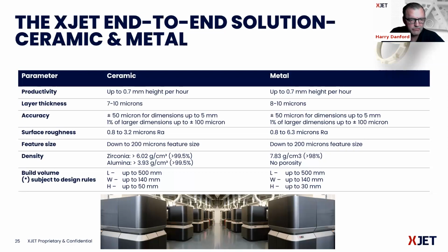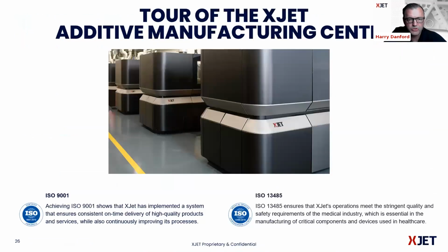In terms of the densities that we're achieving, basically for ceramics, 99.5% full density, kind of the standard density in terms of grams per cubic centimeter for those particular materials. And then 98.5% for the stainless steel products. The size of the tray for the Carmel 1400 system is 500 millimeters in length, 140 millimeters wide. And then in terms of Z height, our current capability for the ceramic materials is around 50 millimeters, so a little over 2 inches. And with respect to the stainless steel, we're up to around an inch or so, or a little over an inch with 30 millimeters. So roughly 5.5 inches wide, 20-inch long build tray.